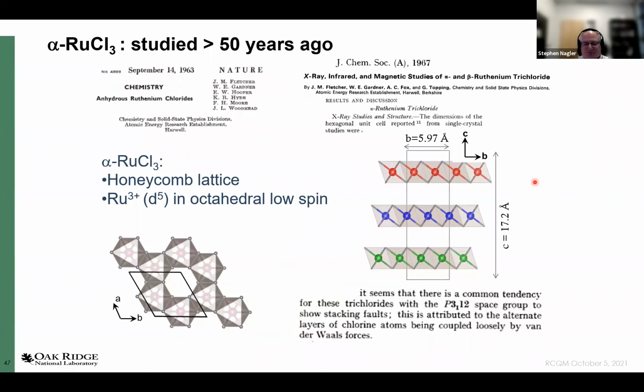And my colleagues like David Mandrus are very particular about not trying to grow crystals out of junk. So we invested a long time taking the junk and purifying it till it was 3N alpha ruthenium trichloride, and then we grew crystals. It was probably too conservative on our part in one sense. The Toronto group went ahead and just used the stuff that you bought, and by vapor transport got some crystals that were sort of the right phase. But we were able to get some really big ones that helped us with our inelastic studies. So we messed around for a couple of years doing that before we really got the samples we wanted. So that was quite a long time.